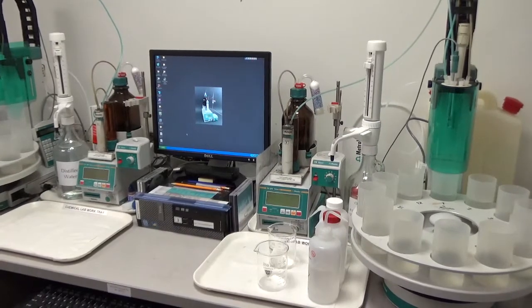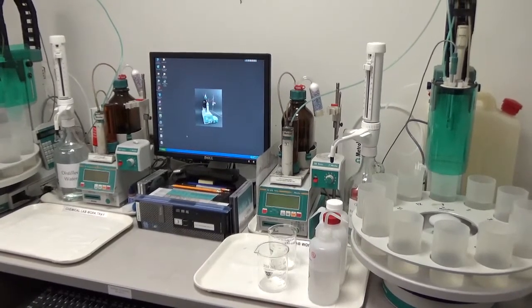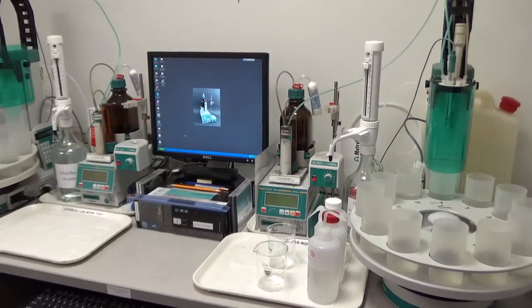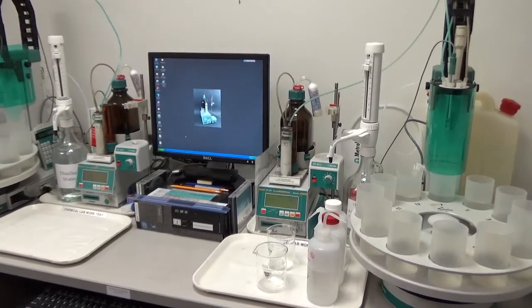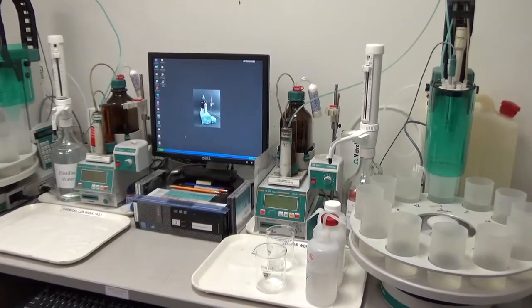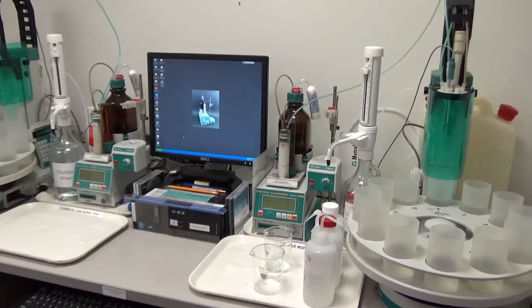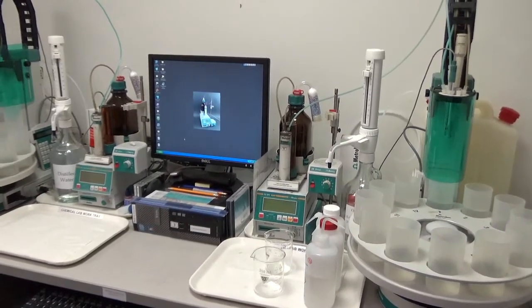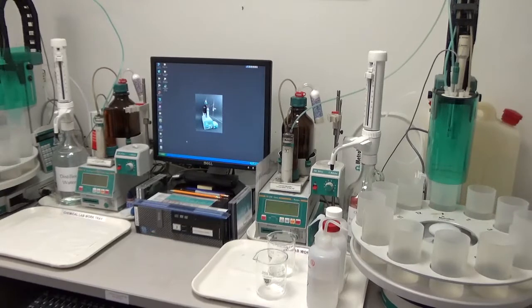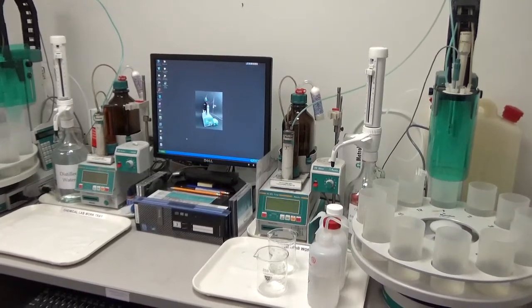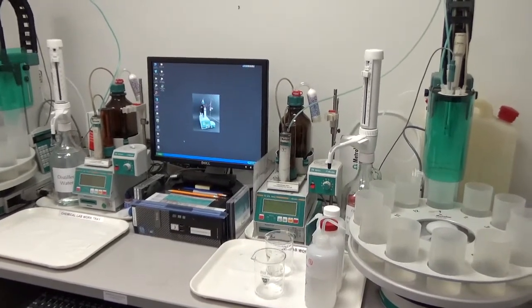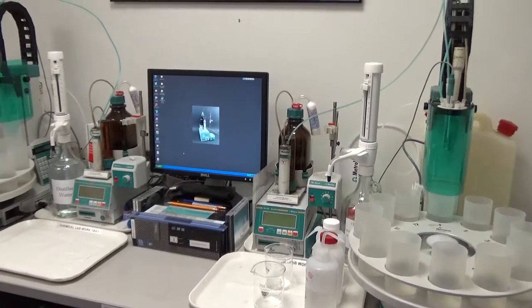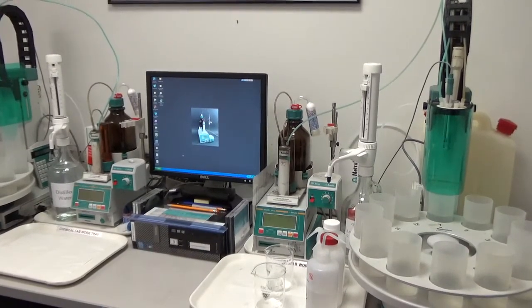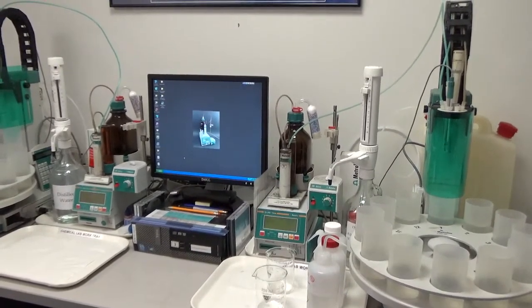When we do acid soluble chloride, we digest 10 grams of pulverized concrete sample in diluted nitric acid, 1 plus 7 nitric acid. We digest the concrete powder in the nitric acid and then we do the filtration. We take the filtrate and analyze it for chloride using silver nitrate as the titrant.